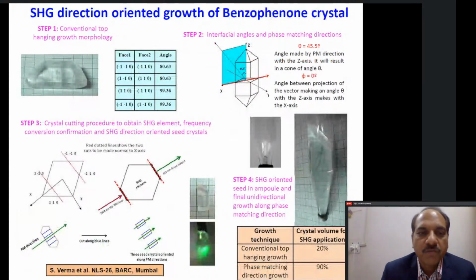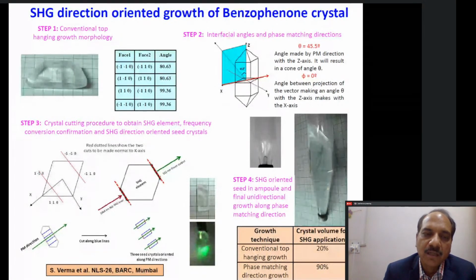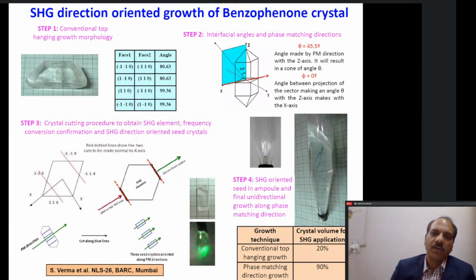Although we had shown the principle by growing an ADP crystal, we thought we should try it and validate it further. So we took a benzophenone crystal, which again is a very good material, and which again grows in the form of a bipyramid morphology if you grow it naturally. So we thought, why not try the same thing in the case of benzophenone crystal. The first step was conventional top hanging geometry. This crystal was grown, which is a bipyramidal morphology crystal.